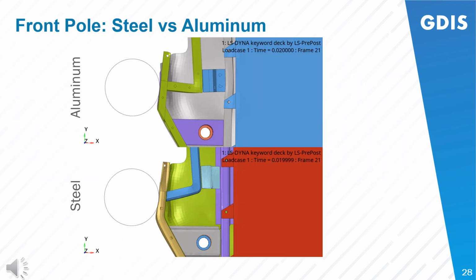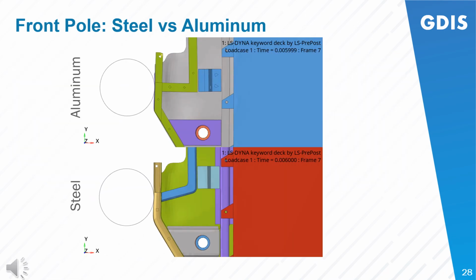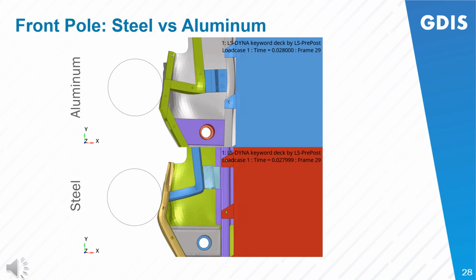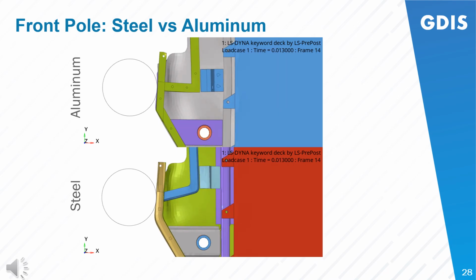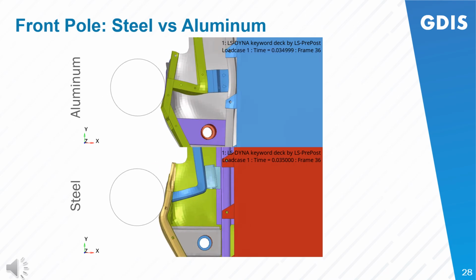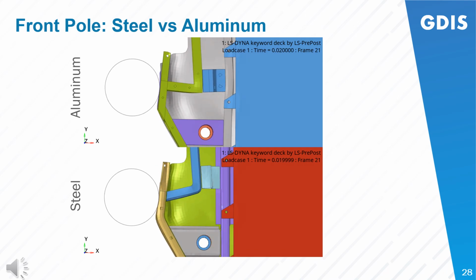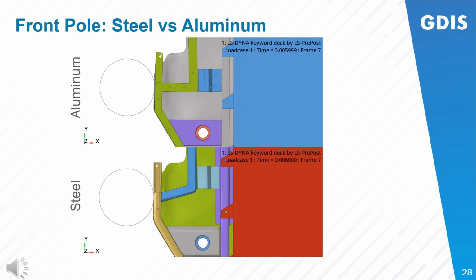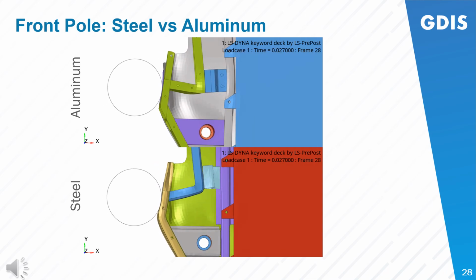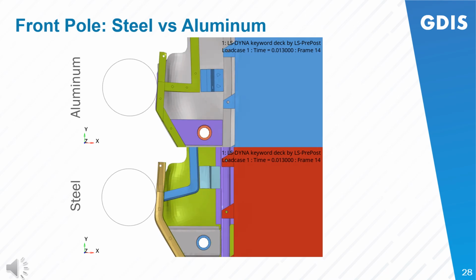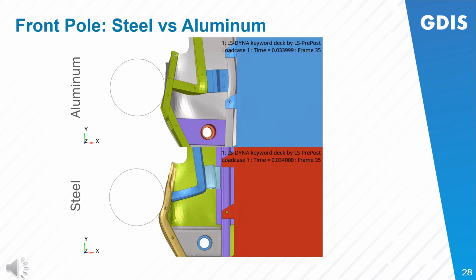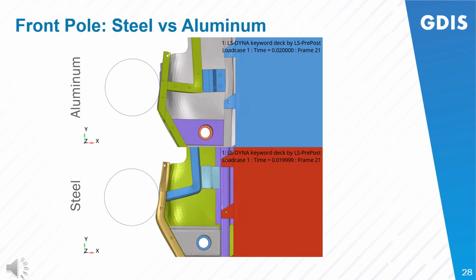And finally, this shows a head-to-head comparison between the aluminum on top and the steel on the bottom. In this particular load case, it's a view from the bottom. You could see the pole. Both images are synchronized. The pole is moving rearward. The top aluminum solution is really dependent on intrusion prevention.